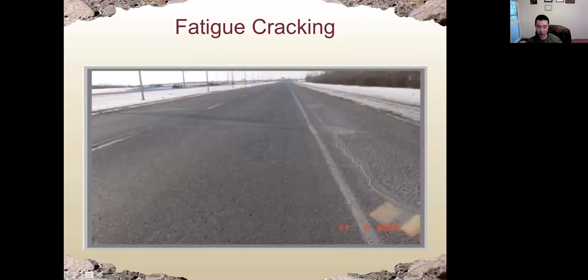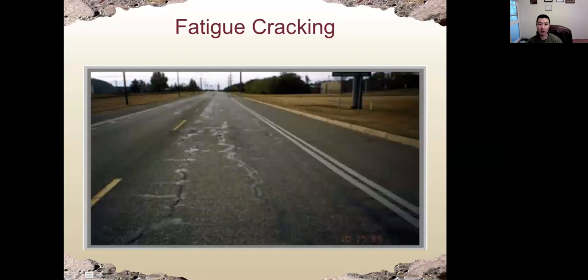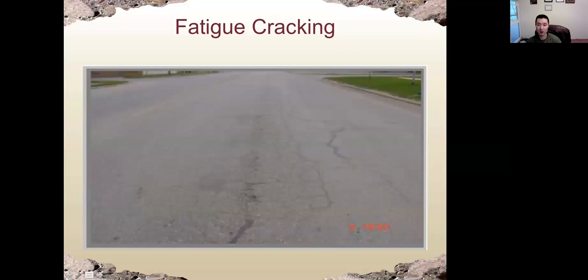This is called fatigue cracking. Fatigue cracking is caused by repeated traffic loading, and also because of the aging process of asphalt. The asphalt becomes too rigid, and that will cause asphalt to crack under fatigue load. The cracks will be interconnected to each other. Like we can see from here, this is a very common type of cracking for asphalt. I believe everybody has seen that type of cracking before. And also here, fatigue cracking.